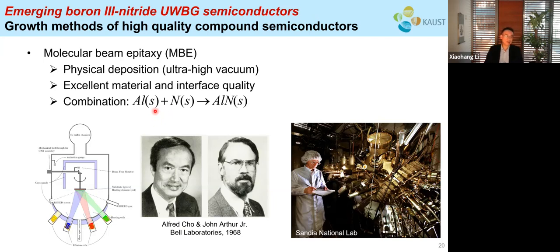This growth happens in ultra-high vacuum. For example, if you want to grow aluminum nitride, the aluminum atoms and nitrogen atoms will sublime from their solid sources and then move towards a heated substrate and combine into a solid molecule, layer by layer on the heated substrate.